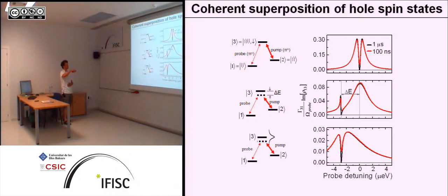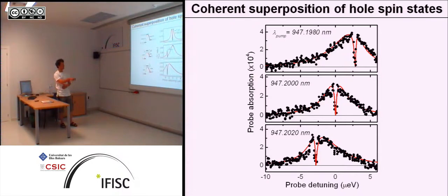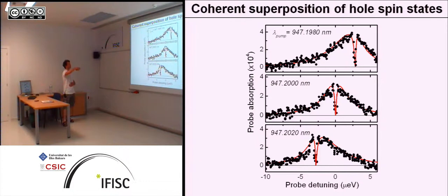The effect of a detuning of pump and probe laser now will be this one, that this dip will move to the side while the maximum resonance will stay at 0 detuning, which is not what we actually see. So to adapt our theory, what we did is we broadened this excited state just by convolution with the Lorentzian line here. And then suddenly this overall spectrum changes to this shape. And this is pretty much what we observe in the experiment.